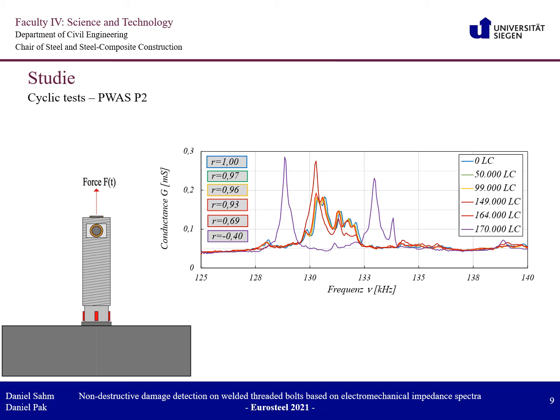The EMI measurements were evaluated by analyzing the conductance spectra. The conductance spectra showed that the amplitudes increase with increasing number of load cycles and thus increasing damage. You can also see a shift of the resonance to lower frequency ranges. In the last test series with 170,000 load cycles, it can be seen that a second amplitude appears at about 133 kHz. Here you can see the first amplitude and here you can see the second amplitude. The diagram clearly shows that the correlation decreases with increasing number of load changes.